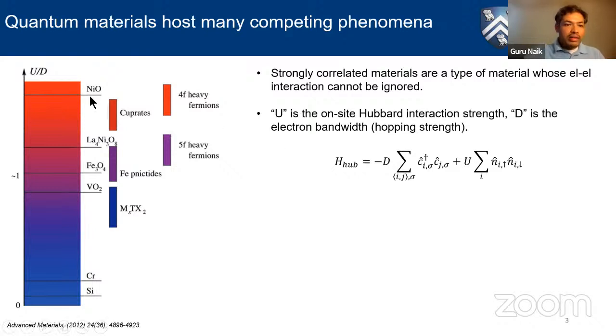And if we plot all the materials, conventional to the quantum materials, as a function of this U divided by D, which is the on-site interaction strength divided by the hopping interaction strength, then we see that all the conventional materials like semiconductors, metals, they all simply fall in this region where U is very small compared to D. So it's basically just delocalization of electrons. We know how to solve them. But in the case of quantum materials, it's U that is stronger or comparable to D, or even stronger, where we see many body effects dominate.